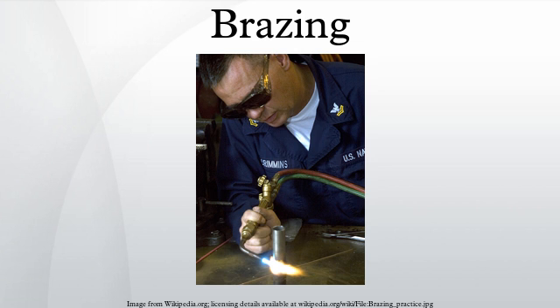Tin facilitates wetting of iron, nickel, and many other alloys. Copper wets ferrous metals that silver does not attack. Copper-silver alloys can therefore braze steels silver alone won't wet. Zinc improves wetting of ferrous metals, indium as well. Aluminium improves wetting of aluminium alloys. For wetting of ceramics, reactive metals capable of forming chemical compounds with the ceramic can be added to the braze.